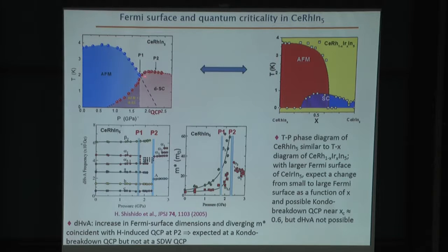So just by simple inspection, the phase diagram that's constructed by replacing rhodium by iridium, shown here, is very similar to this temperature pressure phase diagram of pure cerium rhodium indium-5 (CeRhIn5). And we know that from de Haas van Alphen measurements, that the Fermi surface of cerium iridium indium-5 (CeIrIn5) is so-called large. That means it has comparable de Haas van Alphen frequencies as in cerium rhodium indium-5 (CeRhIn5) at these high pressures.